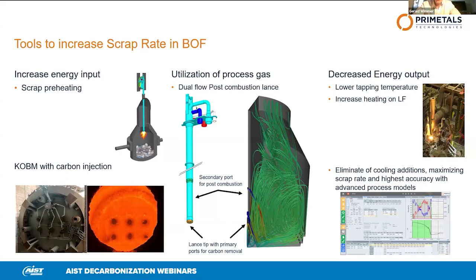Another way to use the calorific value of this gas is to do post-combustion to CO2 already partly in the converter. This is happening in our process standard-wise to 10%. So if we increase the so-called post-combustion ratio to 20 or 30%, we can increase the scrap rate again by some 5%. And last but not least, of course, we have to minimize the energy losses.